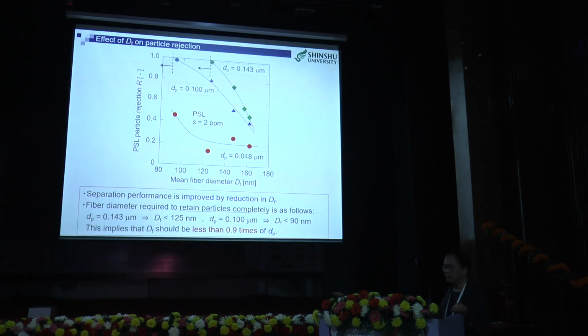So this implies that fiber diameter should be less than 0.9 times of particle diameter to retain them perfectly.